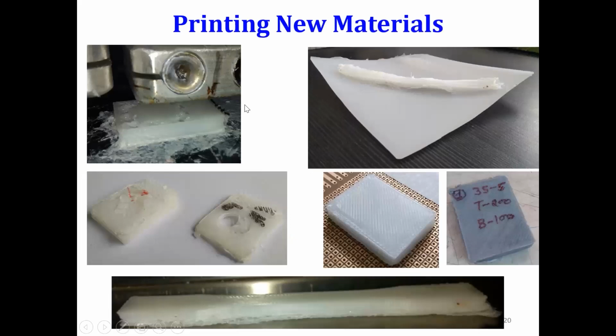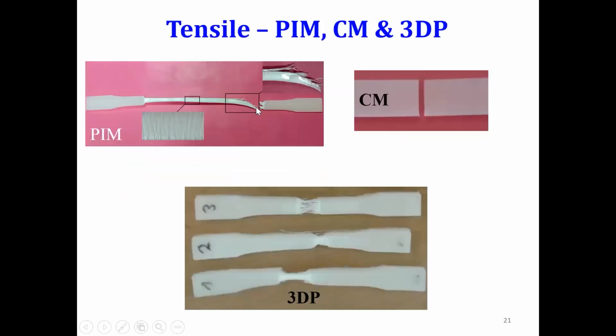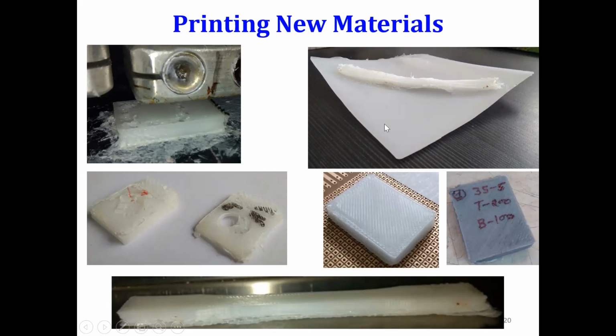Okay, so this is what our first experience was when we started with high density polyethylene, as this material was never tested for 3D printing and not commercially available as filaments, and that's why we chose it to explore. You can see the warpage. This is the sample to be printed. When we were printing, in the middle of the printing, it lifted off the plate onto which it was getting deposited. This is also made of high density polyethylene, because you need a compatible material for deposition. So this is where the warpage creeps in, and there are insufficient material flows.